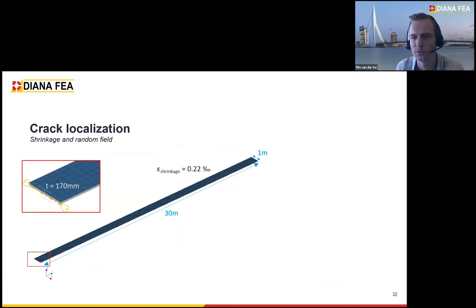I would like to quickly show a second example of crack localization, and that's typically for shrinkage. In this model, we modeled a small slab of 30 meters. It's a slab on grade. On the left side, we have a symmetry axis. So technically the slab would be 60 meters long, and we're going to apply a shrinkage of 0.22 per mil.